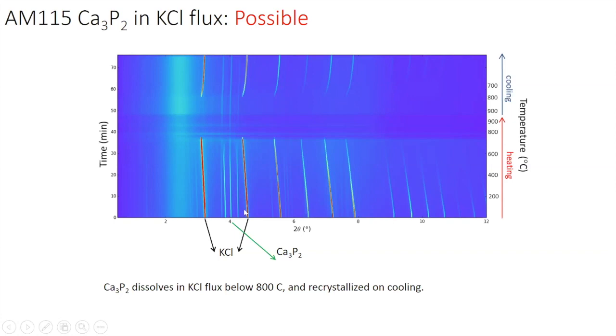So these red lines here are the flux, which in this case is potassium chloride. And these are diffraction peaks from a powder of calcium phosphide that we made. So you can see that as you raise the temperature, the diffraction peaks are there, and then at a certain point they disappear, just like around 750 degrees or 800 degrees. And that means that the potassium chloride melted. There are no more diffraction peaks. You can see that we have only weak diffraction peaks from the calcium phosphide in this region. And so we would construe then that the calcium and phosphorus dissolved into the flux.